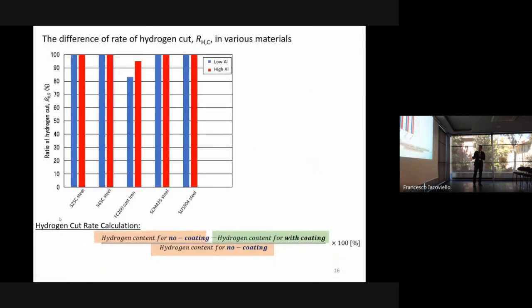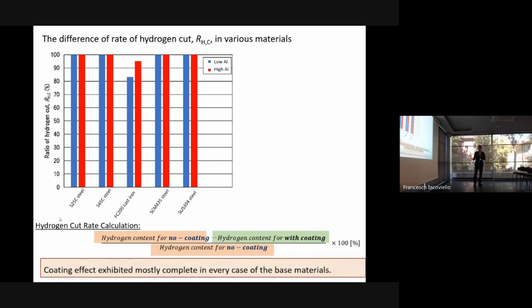So this is the difference of the rate of hydrogen cut, RHC, in various materials. Mostly the RHC shows 100%, except for cast iron. The coating effect was exhibited almost completely in every case of the base material.